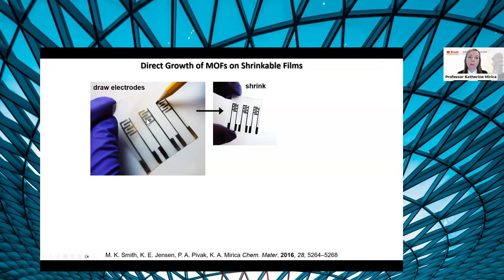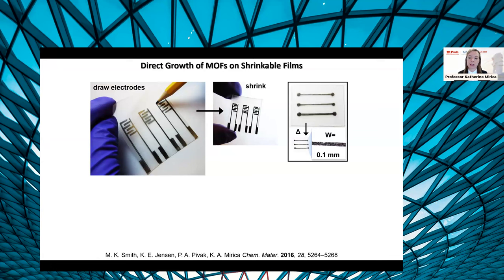Second, we reasoned that by implementing these graphitic electrodes in our device, we could achieve good ohmic contact of the framework materials, which are semiconductive in nature, to this graphitic electrode, basically promoting good electronic connection between the electrode and the device that we're using for sensing.